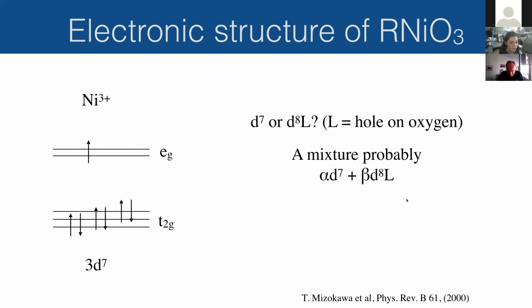But first, let's introduce the electronic structure of nickelates. So as I mentioned, nickel 3+ is quite unfavorable. It exists, but not in very many cases. And it turns out that nominally, of course, the nickelate should be nickel 3+, but in fact, it seems that they use this proximity to oxygen in order to stabilize the nickel orbitals a bit better. And they suck one electron out of the oxygen. So you will often see the electronic structure described more like this, D8L, where L represents a hole in the oxygen.